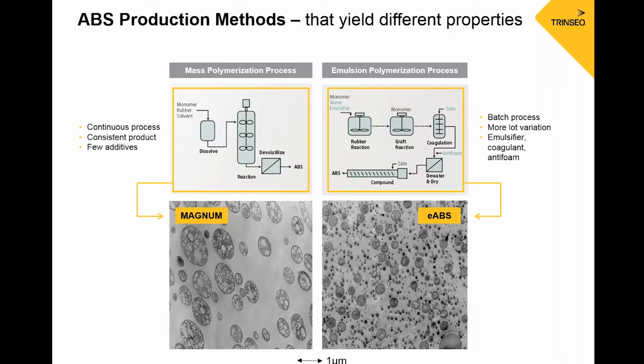On the top right, the emulsion process is a good bit different. So you first are building the rubber, and that is essentially a latex process where water is the continuous phase, and you need an emulsifier in that process. And then that rubber goes to a second stage where it's combined with styrene and acrylonitrile, and that SAN phase begins to polymerize, and that turns into a grafted rubber concentrate. So it's a heavily loaded rubber concentrate, and then there are more additives of salt and anti-foam agents that are used, and then that water has to be taken off of the material and dried.